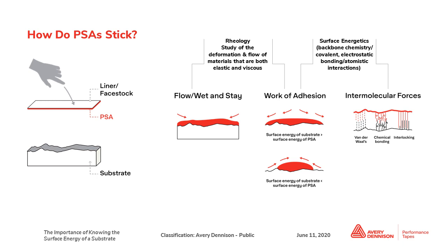Now, if you combine that with the surface energetics between the adhesive and the substrate, these are intermolecular forces, things like van der Waals attraction and chemical bonding. You want both of those elements to be maximized as much as possible for the best bond. Adhesive manufacturers and tape manufacturers have way more control over the rheology of the adhesives they formulate as opposed to the surface energetics of the adhesives they're working with. So you'll learn later why rheology kind of saves the day for bonding to different types of surface energies.